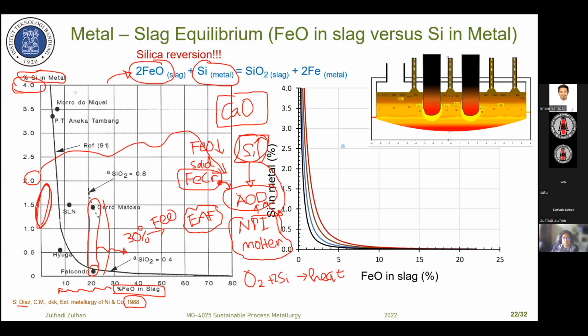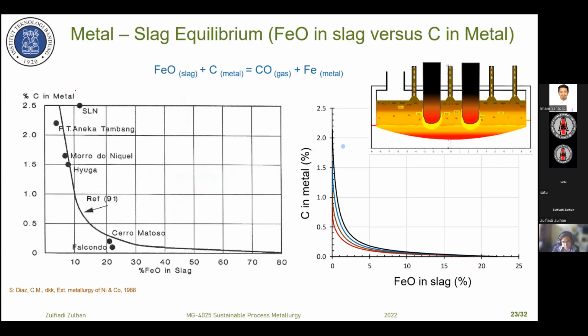So we can adjust the silicon content. We can adjust it by adjusting the iron oxide in the slag, and for sure, we can adjust the iron oxide in the slag by adjusting the reductant, the coal or carbonaceous material, which is added into the rotary kiln. This is the important one in order to adjust the silicon content in the metal. Similar to silicon, carbon also has a similar behavior. So if you have low iron oxide content, you have high carbon content.